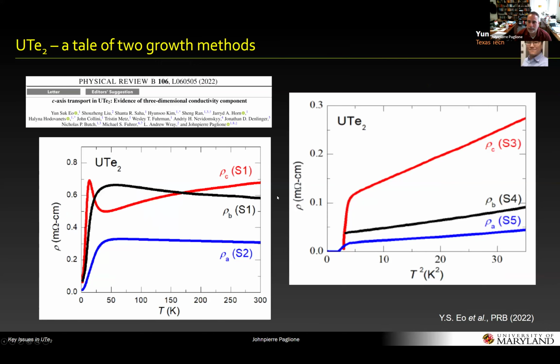This dimensionality question is of course important. We first studied this just by doing very careful transport measurements. And even from here, you can already see that what was first reported, the A and B axis resistivities, are about a factor of 2 different, but they look nominally similar in temperature dependence. When you measure C-axis resistivity, there's something quite interesting that appears, and it's this metallic behavior that has a peak at much lower temperature than the A and B counterparts. And we're still studying this.